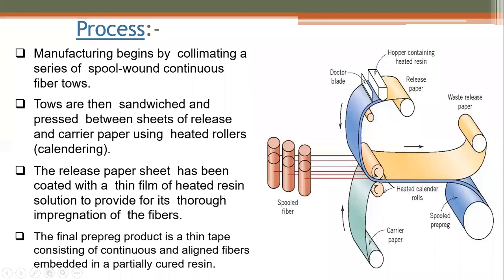So the release paper and carrier paper are the two outer layers, and in between them the sandwich panel of the spooled fibers is pressed using the heated rollers, also known as calender rollers. That is known as calendering. The release paper sheet is coated with a thin film of heated resin solution to provide thorough impregnation of the fibers.